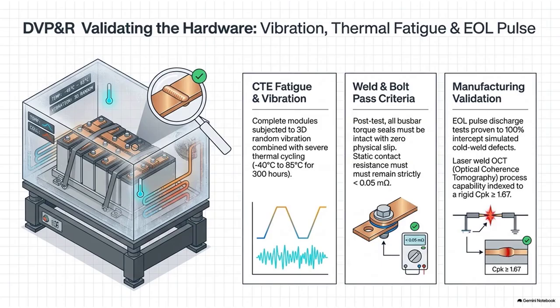And measuring something down to the micro-ohm level isn't as simple as touching two standard multimeter probes to a piece of metal, right? Because the resistance of the probes themselves would throw off a reading that small. Exactly. Standard 2-wire multimeters are useless here. They utilize a 4-wire Kelvin resistance measurement technique. How does that work? It uses 2 wires to inject a highly precise, known test current across the joint and a separate, dedicated set of 2 wires to measure the voltage drop directly at the connection points. This entirely eliminates the resistance of the test leads and the contact resistance of the probes themselves, isolating the true absolute resistance of the weld or bolted joint.